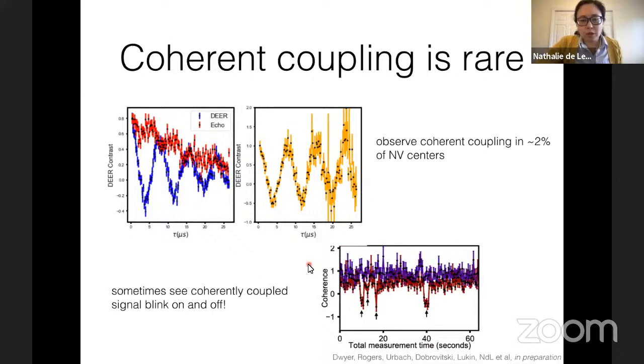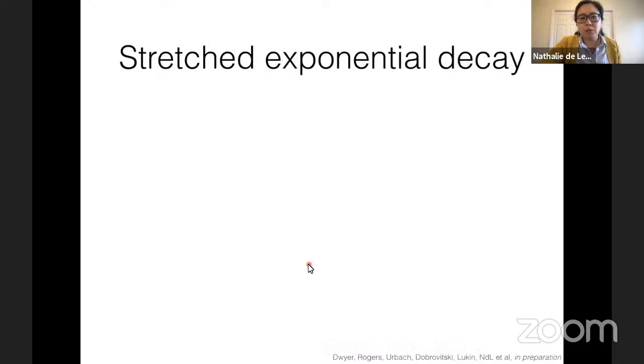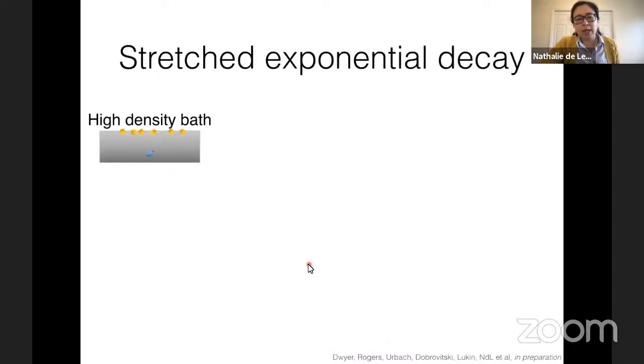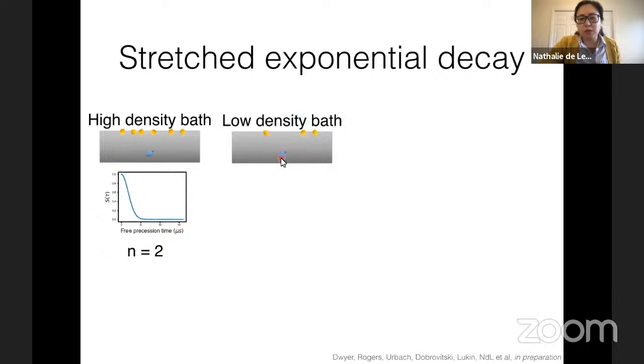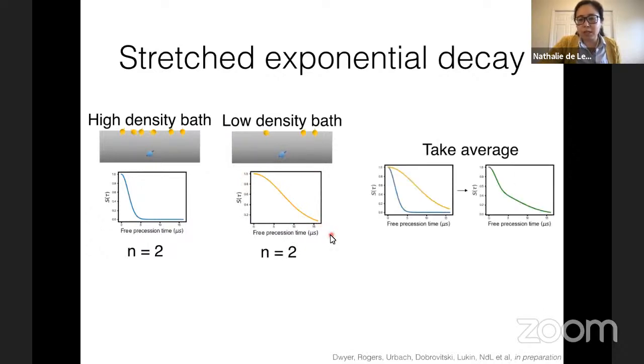Okay, so those are our 3 puzzles: you don't see statistical variation, you never see coherent coupling, and then we also have this weird stretched exponent. So one guess at what might give you the stretched exponential decay is, for example, if you imagine that you have an NV center that's talking to a really high density bath, and that gives you this nice n equals 2 coherence decay. But then at other times, it's talking to a low density bath, which also gives you an n equals 2 coherence decay. But if the NV center sees both of these things and averages over these 2 configurations, then what you end up with is something that has an n that's less than 1. So it appears to be a stretched exponential.